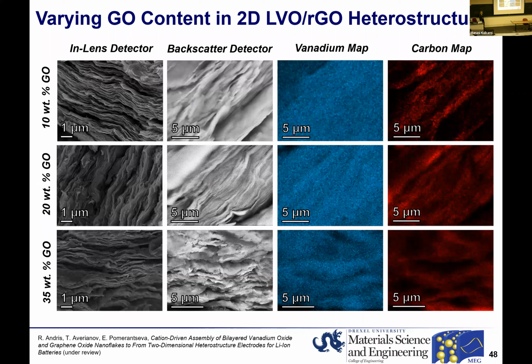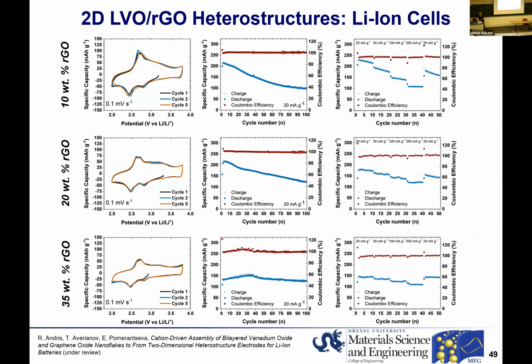heterostructures. So this, of course, doesn't tell us much about the heterointerface, because this is cross-sectional SEM microscopy with the elemental mapping, but we do see some layers of carbon and some layers of vanadium that tell us that at least some heterostructuring does occur. We just sent these samples to Michael, so we are hoping to see a better resolved chemical analysis of these materials. And look at the electrochemistry.